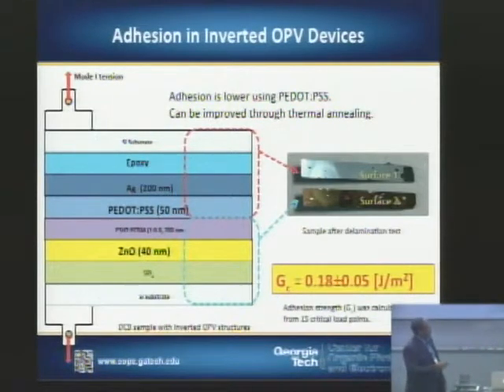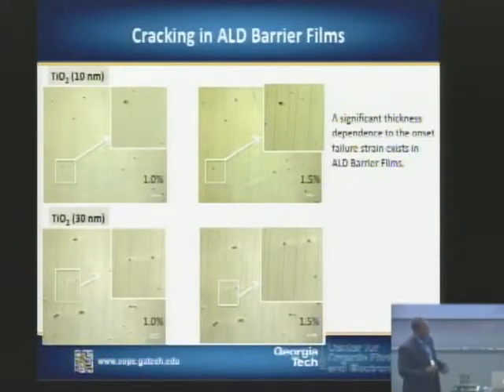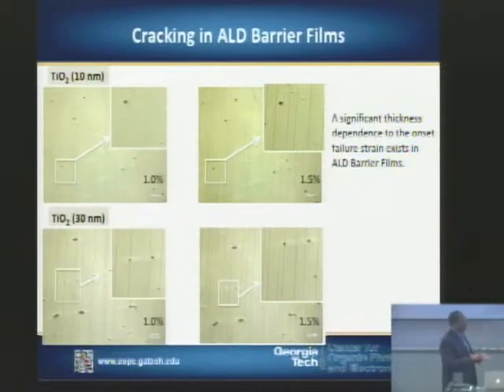Beyond looking at just the organic photovoltaic, when we start looking at these oxide barriers, this is one particular case where we're looking at titanium dioxide as a barrier film. Here we're strictly looking at the strain to failure. This is a film that is about 10 nanometers in thickness versus a film that's about 30 nanometers in thickness. When we look at titanium dioxide, there is something called the critical thickness, beyond which you don't get much additional benefit in terms of the water vapor transmission rate or the barrier performance.